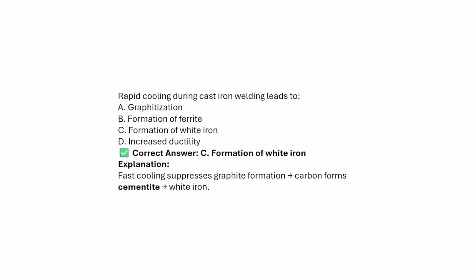Rapid cooling during cast iron welding leads to graphitization, formation of ferrite, formation of white iron, or increased ductility. The answer will be formation of white iron. Faster cooling suppresses the graphite formation, which results in the carbon forming cementite and white iron.